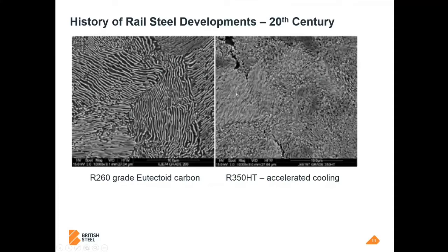So it's a big leap forward for heat treated rails, but it comes with some problems, and we'll discuss that later. But these two grades are widely adopted across Europe as a standard grade and then a premium rail grade. And the smartest operators of networks will use things like R260 grade in the tangent track, straight line track where you don't get a lot of wear. And they might choose to use a premium rail grade like R350HT somewhere like curves on the main line, or tight curves or freight lines, for example, where the contact energy is higher.